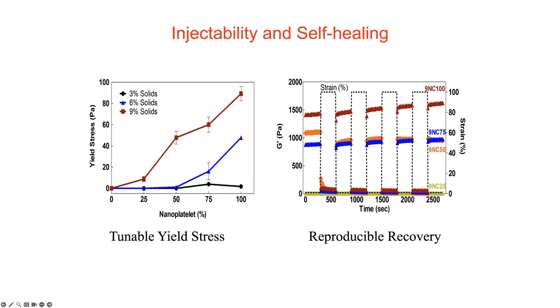And all of these materials have a reversible property. So when you apply force, the G prime here, which is a measure of how solid-like they are, goes down, so they become very liquid-like. And then when you remove the force, they go back to their solid state. And this is a repeatable process. So having this material with these properties is interesting, but we want to see how it works in